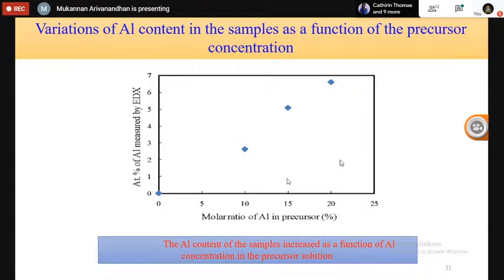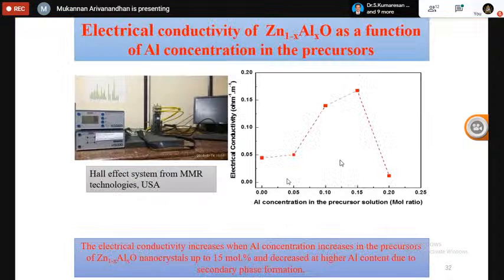And this is the aluminum content variation in the sample with respect to the variation of aluminum in the precursor. Okay. Then the electrical characteristics have been measured, and the electrical conductivity has increased up to 15% of aluminum and then drastically decreased.